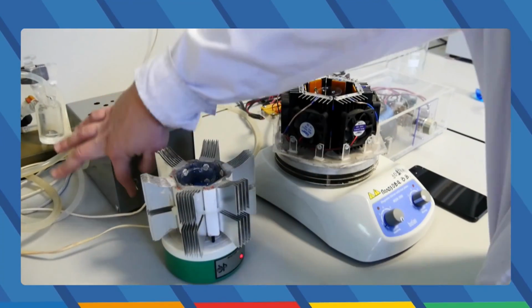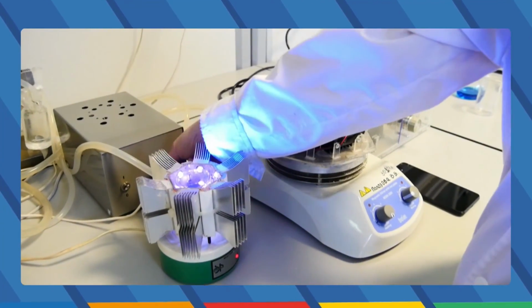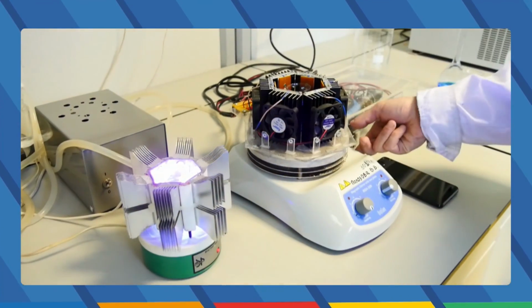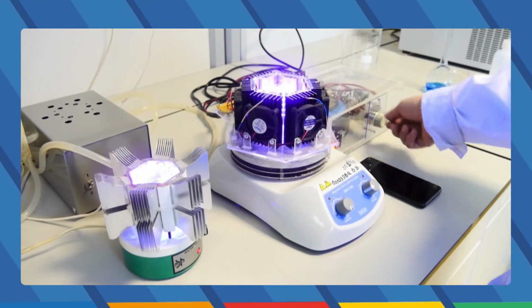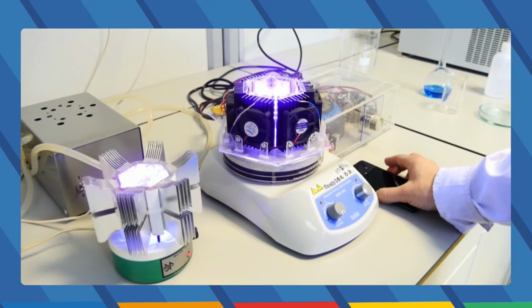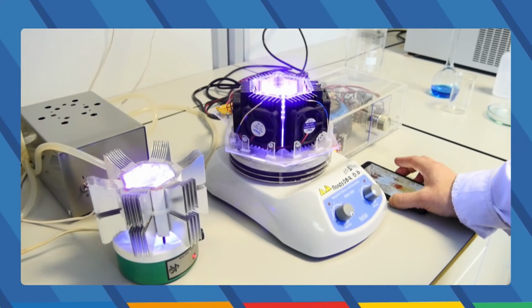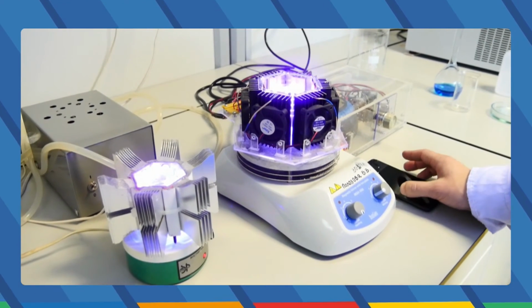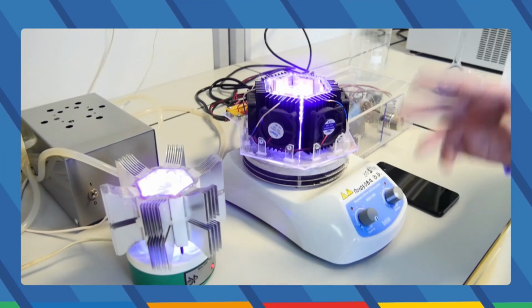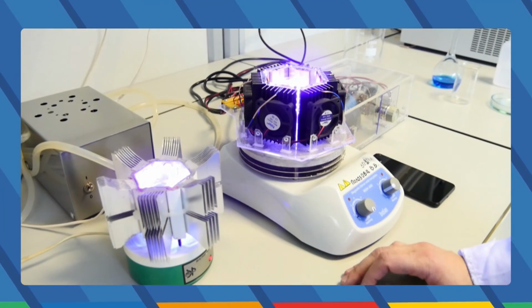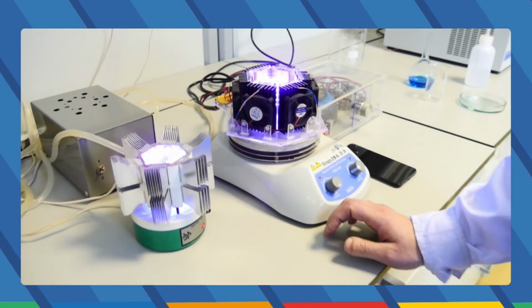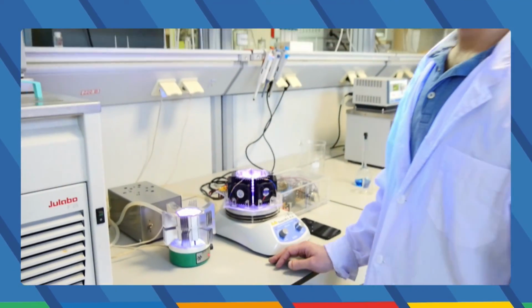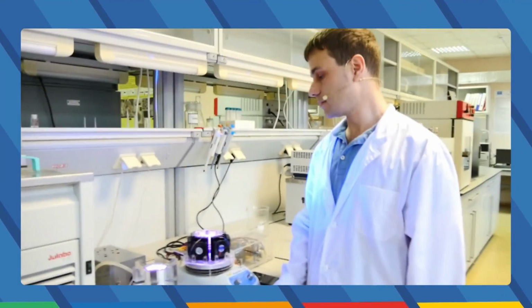And we begin to irradiate them with a UV spectra. So now we begin to count down to 15 minutes, and after this the reaction will be ended, and the solution should be transparent and white without any traces of the methylene blue dye.